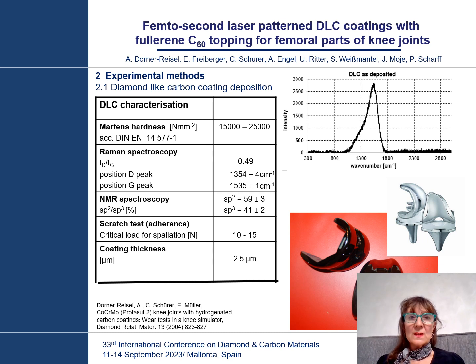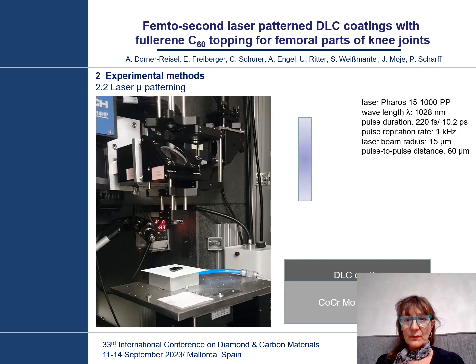Diamond-like carbon coatings were deposited on flat cobalt chromium molybdenum substrates by decomposition of methane. In previous work, we elaborated that a coating thickness of 2.5 micrometers is especially advantageous. And also in this study, we apply a coating thickness of the DLC coating of 2.5 microns.